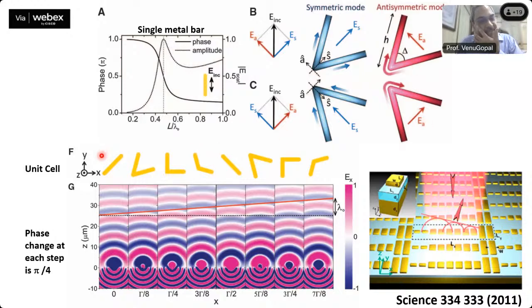Right. Now, the interesting thing which was shown in 2011 was you can align these scattering elements. Let's call these antennas, as per the parlance in the field, right? So you arrange these antennas in different fashion. So now this is your unit cell, which has this set of 8 scattering elements or antennas which are aligned. Now you can have a periodic arrangement of these. Now, if these are put on top of a surface and we shine light from the bottom, each of them is going to scatter the beam in a slightly different way.